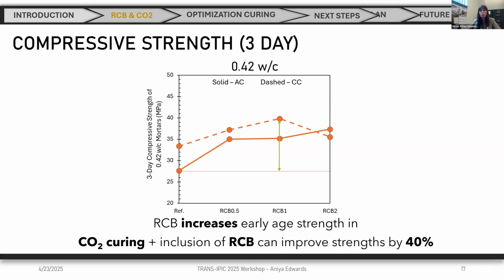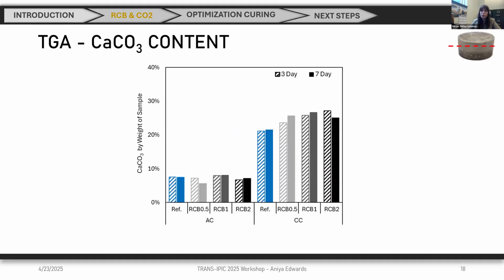And we are talking about an increase of 40% or so. So using these two things together can really give you a much greater early strength, and therefore you will be able to remove the forms earlier or transfer the loads earlier, and therefore you will have much better production.